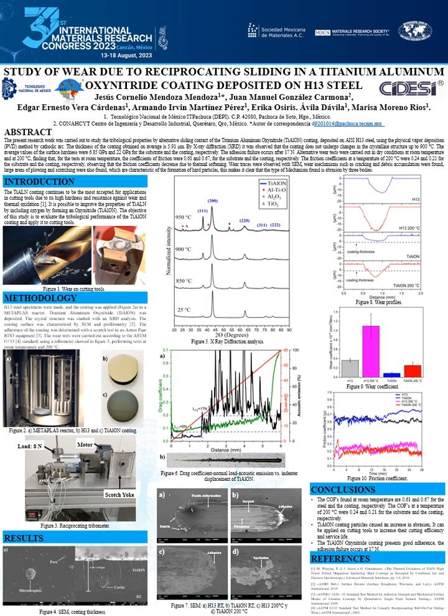Figure 7 shows the scanning electron microscopy of the wear tests carried out by reciprocating movement on the steels. The formation of wear mechanisms such as plastic deformation, adhesion, and debris is found. In the coating, areas with scratches, blistering, and spallation were found.